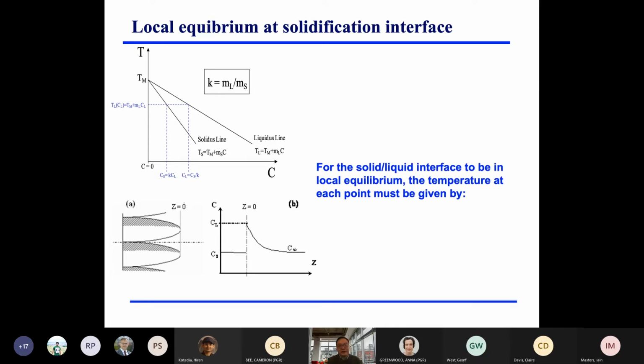So I think in most modeling, whatever tool you use nowadays, we assume a local equilibrium at the solidification interface. That means at the solidification interface, the chemistry of the solid phase, which is at the end of the tie lines here, and the chemistry of the liquid phase are determined by thermodynamic equilibrium states, and those are fixed, right? And then kinetics may play a role, but kinetics look into diffusion. But for solidification modeling, in most cases we use the local equilibrium condition.